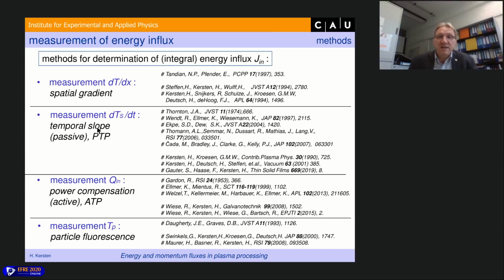What we mainly use is the temporal slope. We measure the heating and the cooling of the substrate during the plasma process. That is what we call a passive thermal probe. This is a passive thermal probe. We just measure heating and cooling of the substrate.